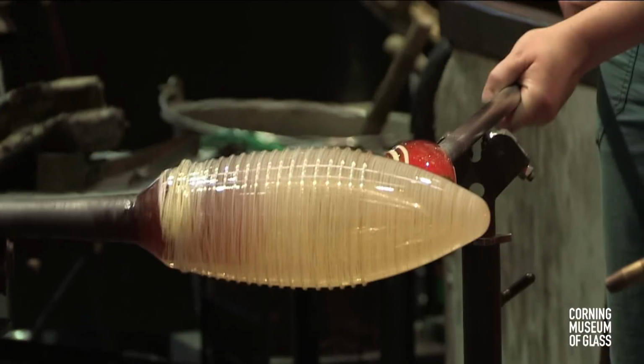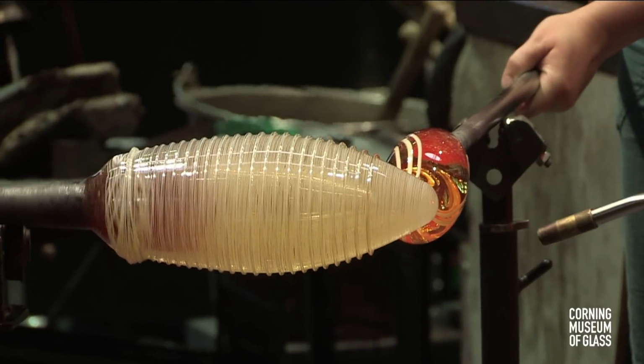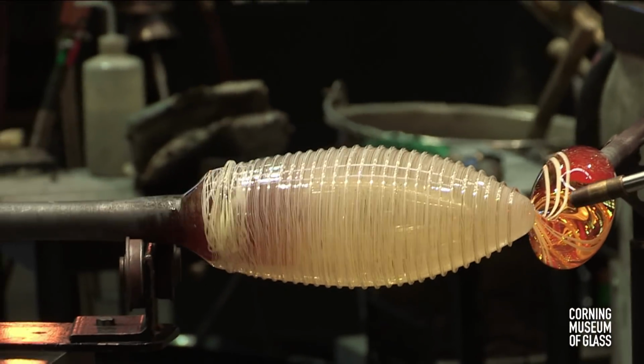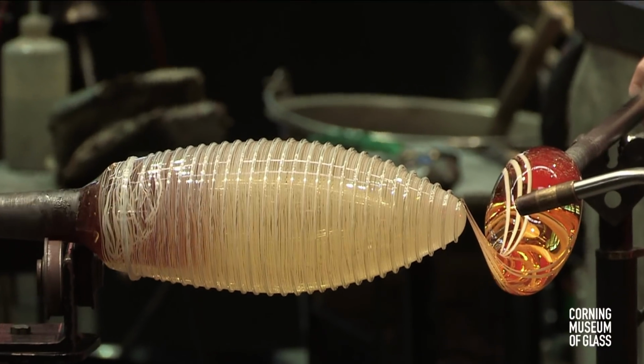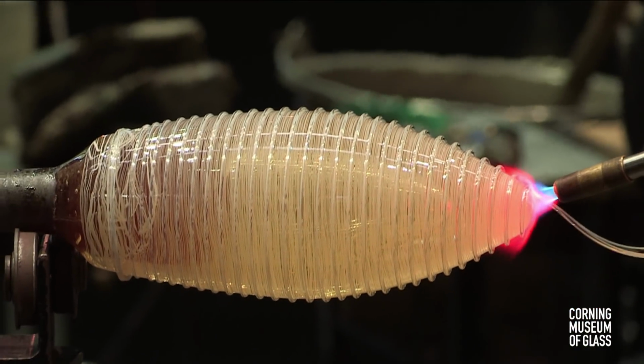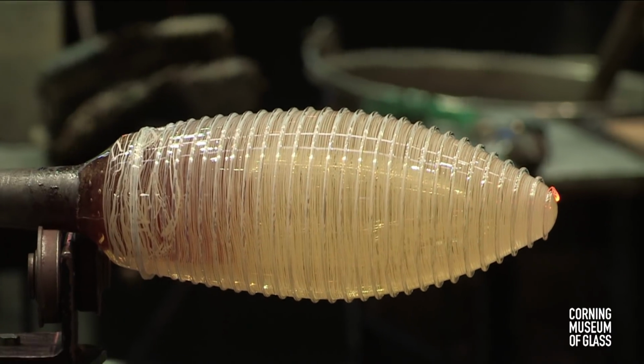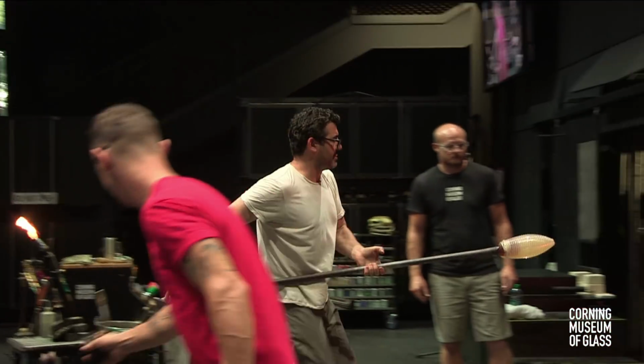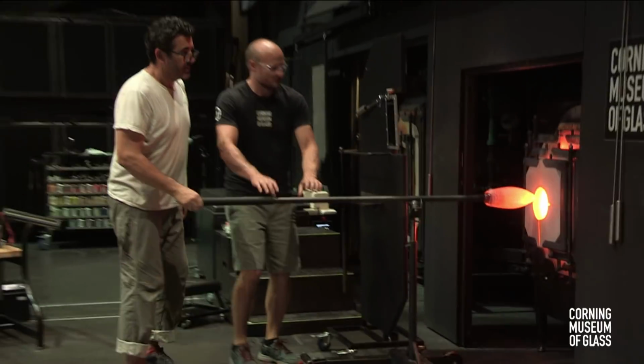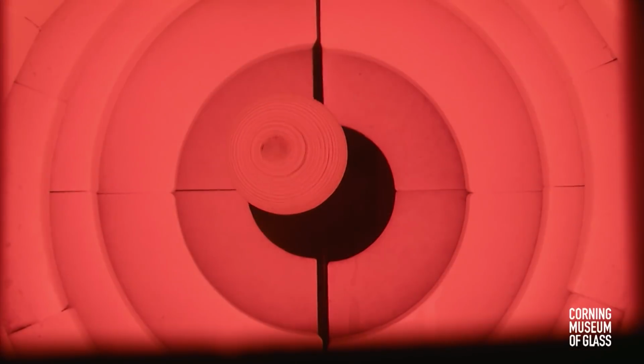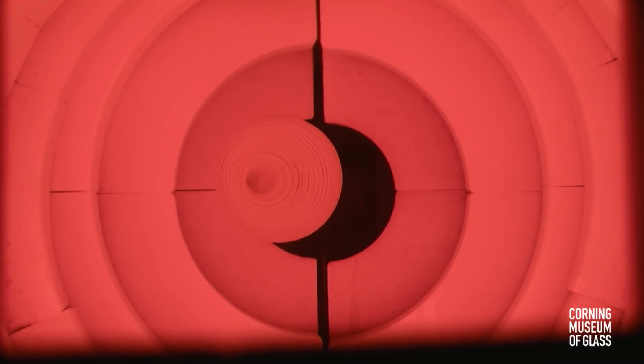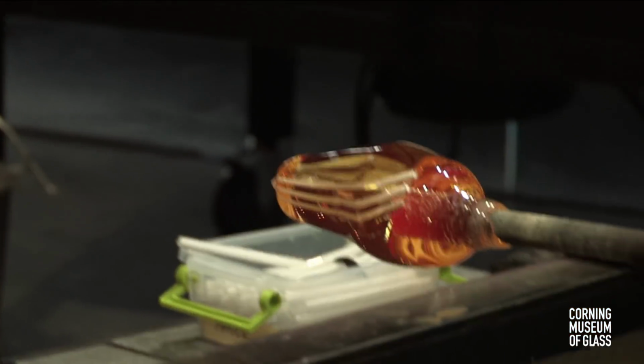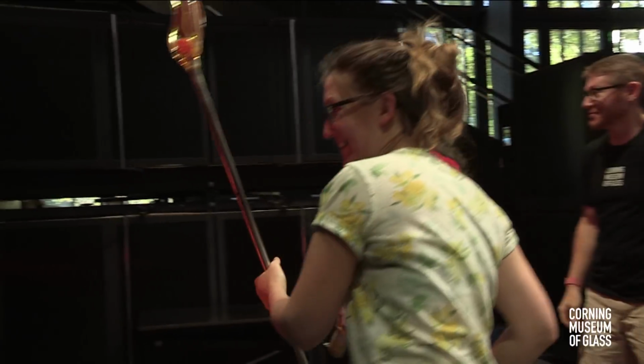Well, they haven't actually let the glass get to the point where it's too cold. So when the threads are going on right now, the gather that Josie has is probably around 15, 16, 1700 degrees. Michael's been keeping the core of his bubble more rigid, so closer to probably 1200, maybe 1100 degrees. But they never stay away from the heat for too long. Yeah. And once those wraps go onto the surface and they melt them down right now, they're not really thin anymore. They actually melt into the bubble that they have. So there's a lot of mass to hold the heat. I think that's probably what they were referring to.